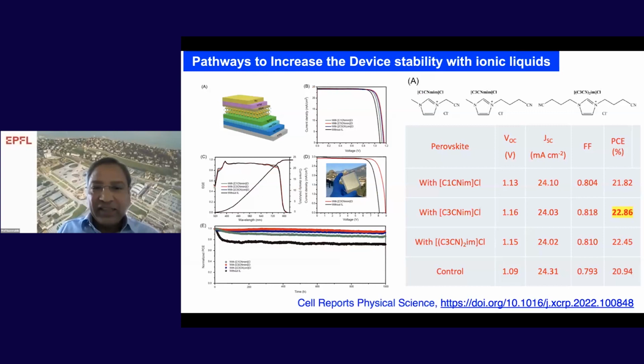So I have taken another example for stabilizing the perovskite composition. So here is the ionic liquid with functional groups. What are the functional groups? Cyanide, cyanide with the long alkyl chain, the cyanide groups with two times substitution. So the purpose here is the cyanide groups should interact with the lead 2+.